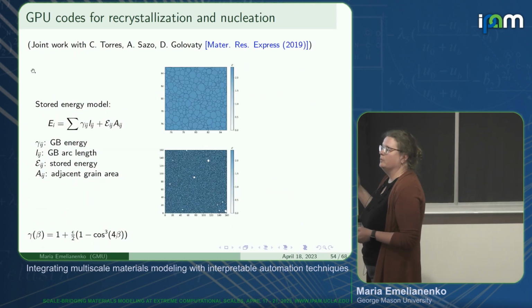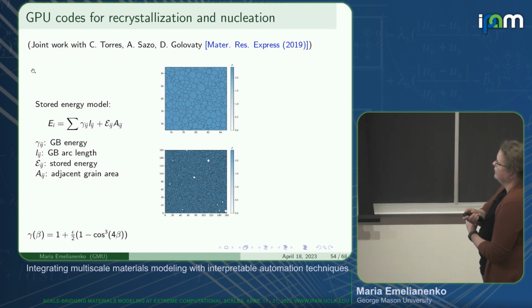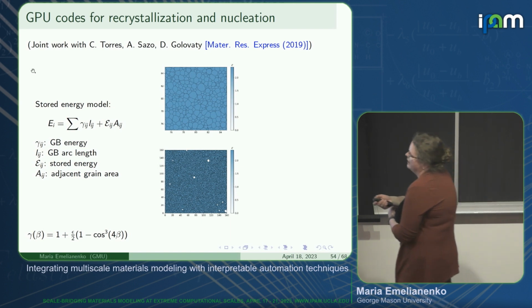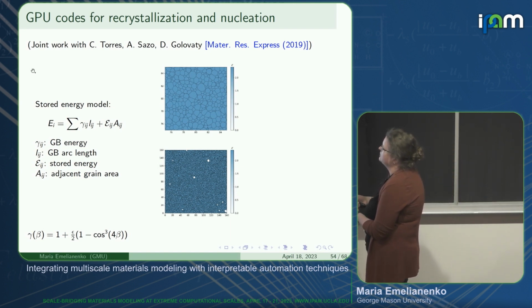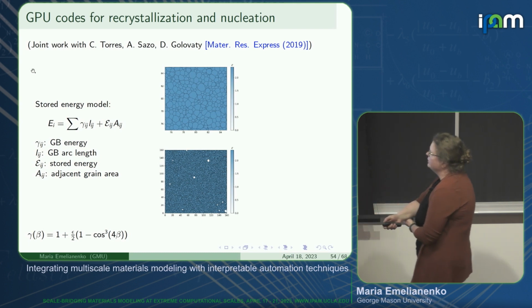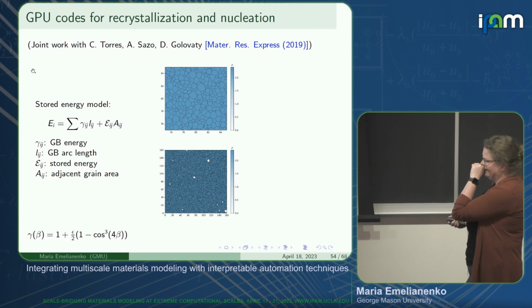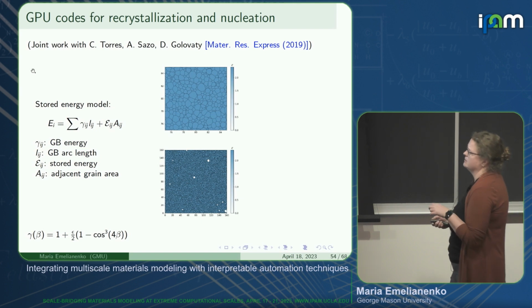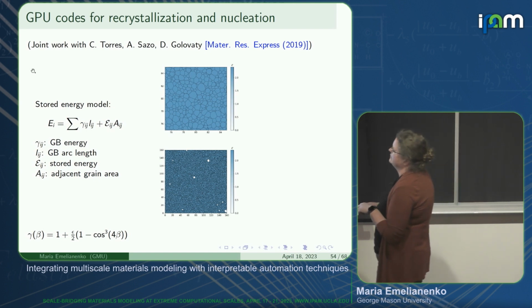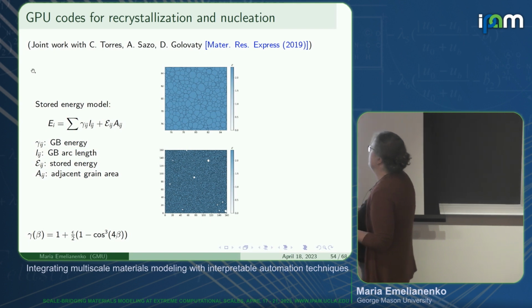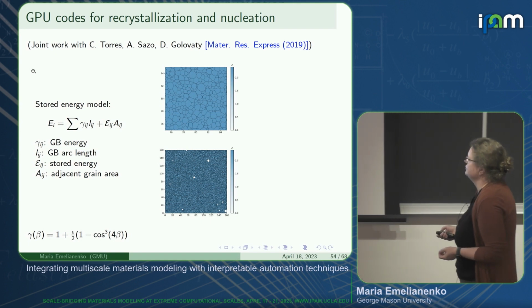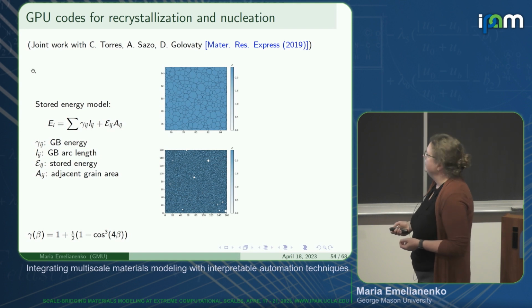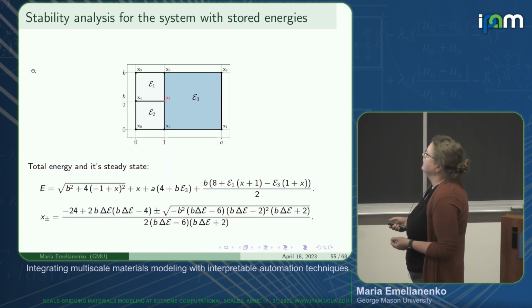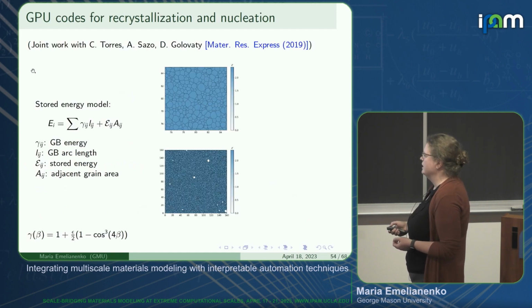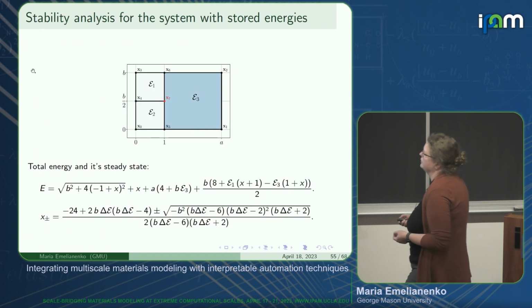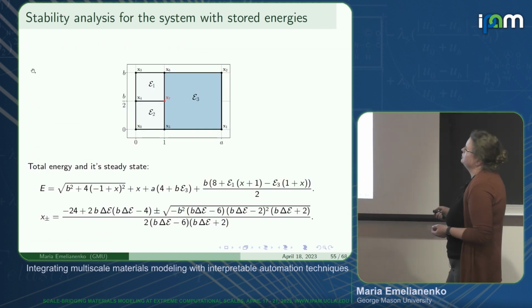One thing we know how to do, and we want to use it in this more complicated context, is we know how to add nucleation. So this is the code that we have available. This is a GPU parallelized code that incorporates stored energy, and that allows us to nucleate grains of specific misorientations. So this is a mechanism that seems to be actually quite easy and not so sophisticated compared to the previous descriptions that we had. We did a lot of work with this particular code, so we actually have the code, and I think it's handling like 1 million grains right now. So we have done development of stability analysis.